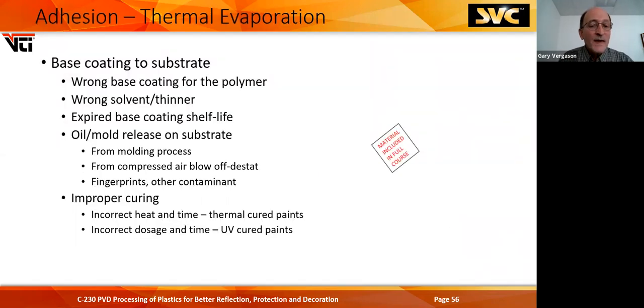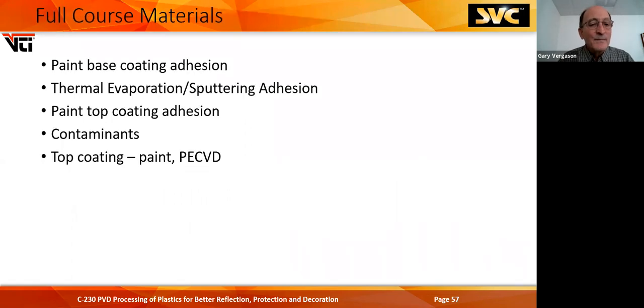Adhesion can be the wrong base coating, wrong solvent or thinner used in the paint, expired, the shelf life's bad. You've got oil or mold release on the substrate. It can come from your blow-off air if you're not cleaning your air up, and or fingerprints. If it's a fingerprint, you can find who did it, because actually Edwards makes thermal deposition machines for forensics. It can be improperly cured. You can be over-cured, you can be under-cured. So there's a lot of little angles here to be knowledgeable about.